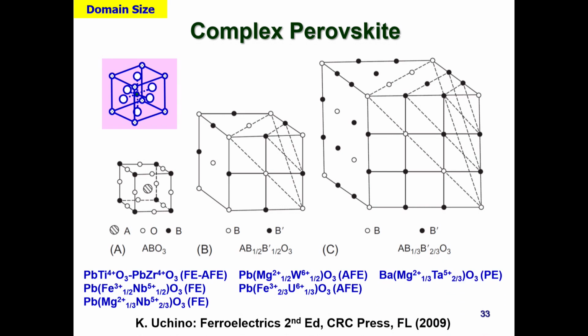So interestingly, the disordered complex perovskite is always creating a ferroelectric, and the ordered materials usually give anti-ferroelectricity. And the 1-2 order, this is nonpolar. And the nonpolar is popularly utilized for the gigahertz, like microwave range, dielectric materials. The reason is not completely clarified, so we need to wait for the physicists' beautiful explanation on this.